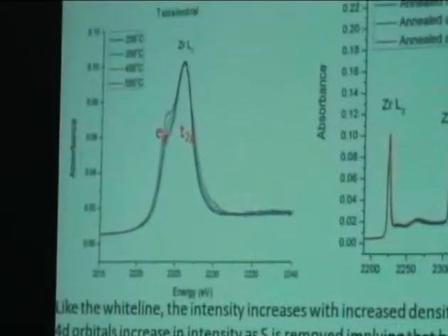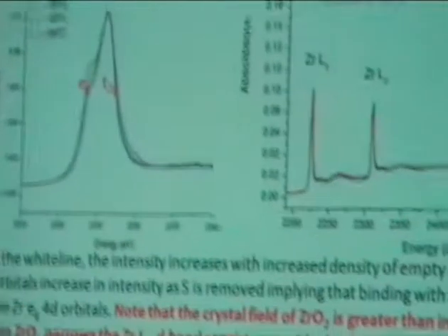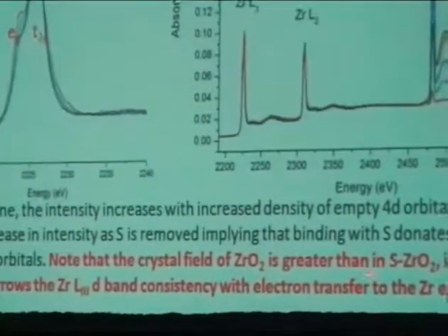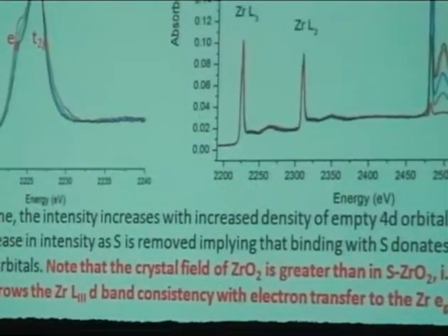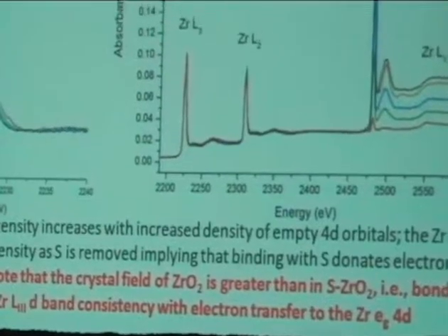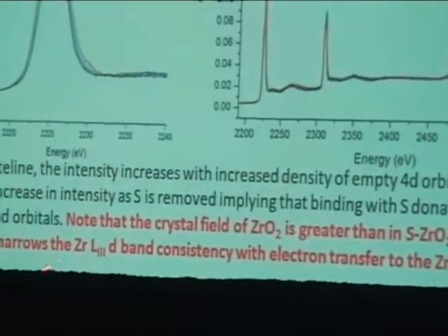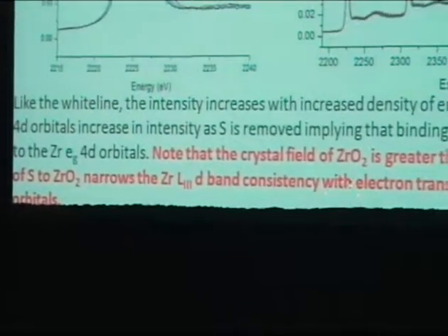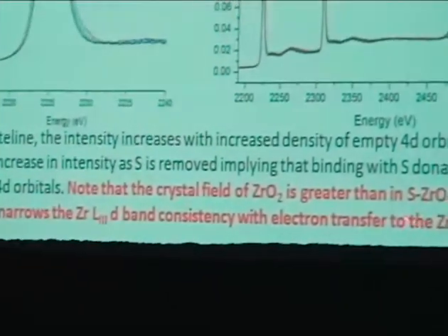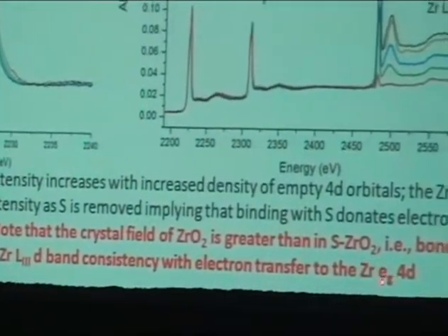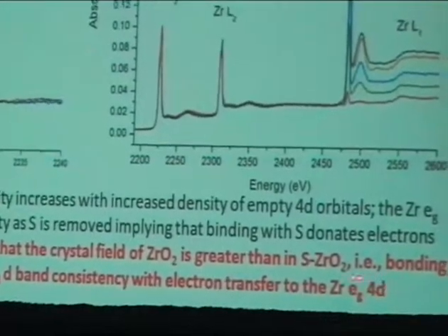So from that, we can draw this conclusion: because the crystal field splitting is smaller in the presence of sulfur, we conclude that the bonding of sulfur to zirconia narrows that, and that's consistent with electron transfer to the zirconium, and specifically into the Eg 4d orbitals.